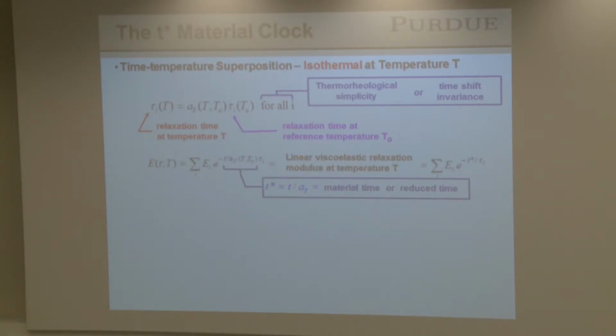The question that we asked, first of all, is how do we put temperature in all of this? And the polymer people call this time-temperature superposition. And what it says is that relaxation time, which is a material property at a temperature T, is related to the relaxation time at a reference temperature T naught by this function A. So A sub T just says how does the time scale of the relaxation in the material change with temperature. Heat up the material, it relaxes faster.